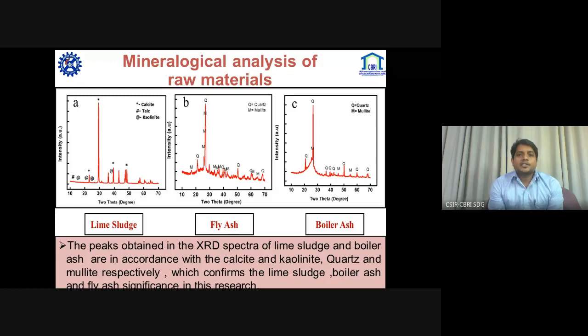On the mineralogical analysis of raw materials, the lime sludge clearly represents calcite, talc, and kaolinite. Fly ash represents quartz and mullite, and boiler ash also quartz and mullite. The thing to note here is that fly ash has more mullite than quartz, and boiler ash has more quartz than mullite. This is due to the greater alumina presence in fly ash in comparison to boiler ash. Boiler ash is more silica prominent, while fly ash has both silica and alumina. So we chose the boiler ash for the nanosilica production. This is the reason.